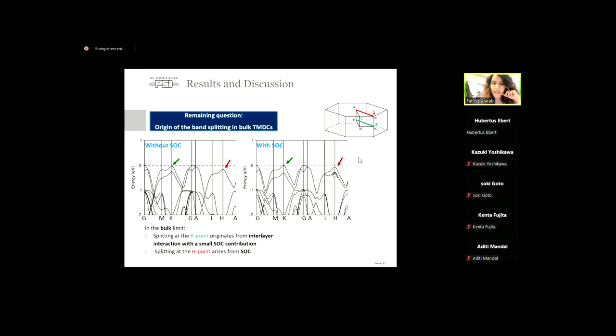So from this, we can deduce that at the K point, the splitting is due to the interlayer interaction because we have a KZ dependency in here, and it's periodic. It goes just like that. So because of the interlayer interaction, the bands will be split. However, at the H point, it's only due to spin-orbit coupling. And this will be our target mainly. So this is where we're gonna look.